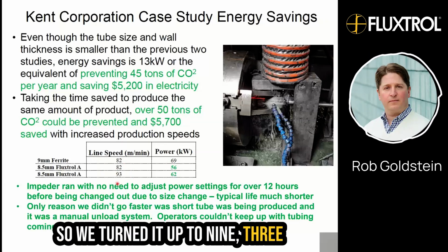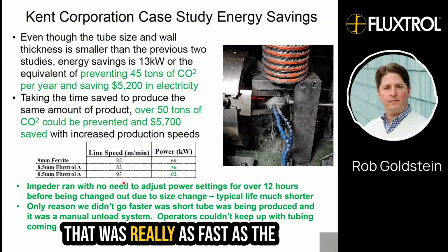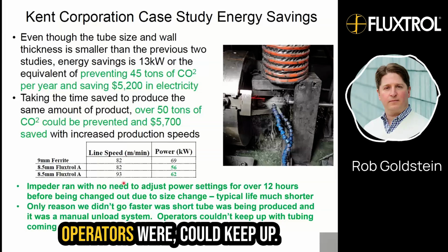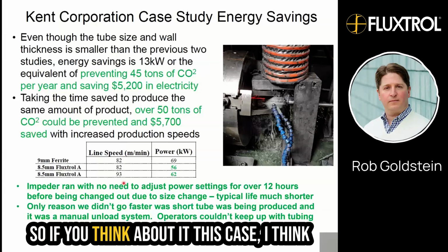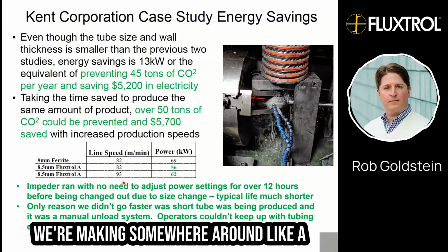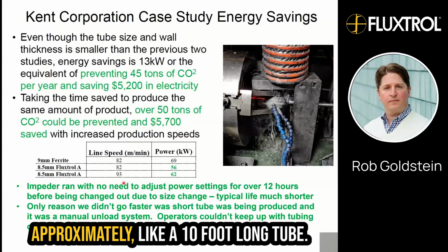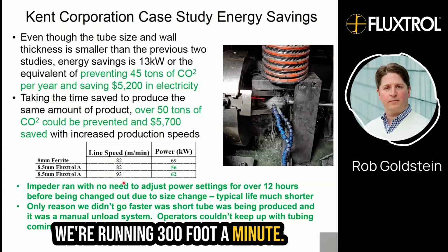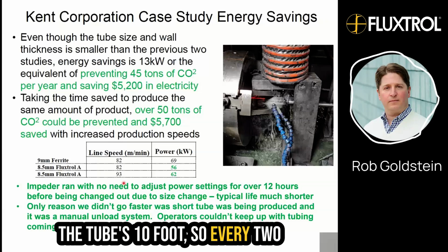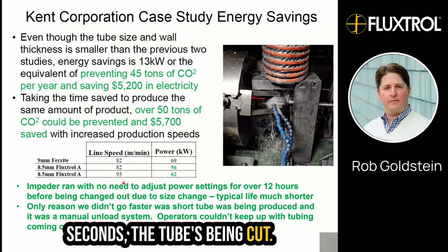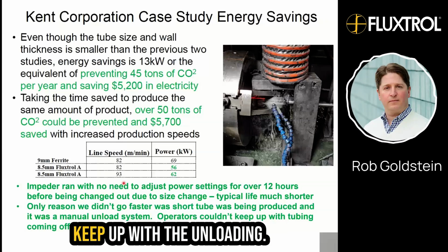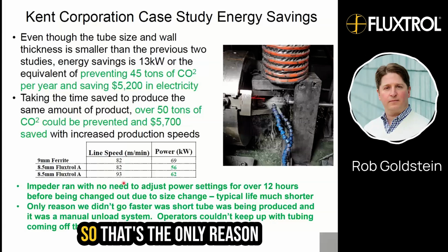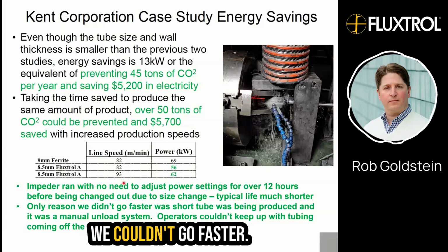So we turned it up to 93 meters a minute, and that was really as fast as the operators could keep up. If you think about it, in this case we're making approximately a 10-foot long tube. We're running 300 foot a minute, the tube's 10 foot. So every 2 seconds, the tube's being cut. And the operators just couldn't keep up with the unloading. So that's the only reason we couldn't go faster.